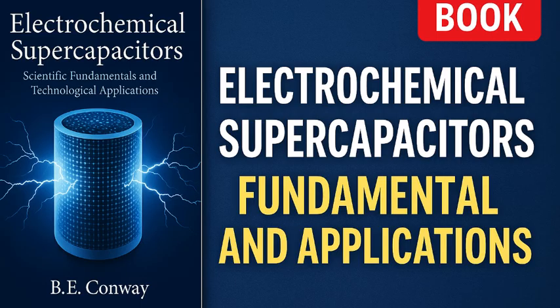Another interesting feature of carbon electrodes is their surface functional groups. Activated carbons often carry chemical groups on their surface: oxygen, hydrogen, sometimes nitrogen if treated, especially around the edges of graphene-like planes in their structure. These can be things like hydroxyl, carbonyl, carboxyl, quinone-like structures. These functional groups can influence capacitor behavior in two ways. They affect hydrophilicity or wettability. A more oxygenated surface is generally more polar and can be wetted better by aqueous electrolytes.